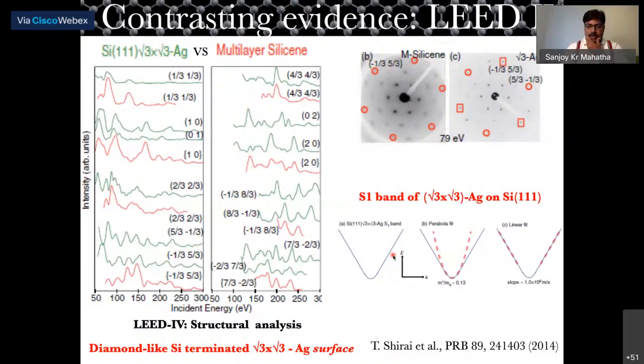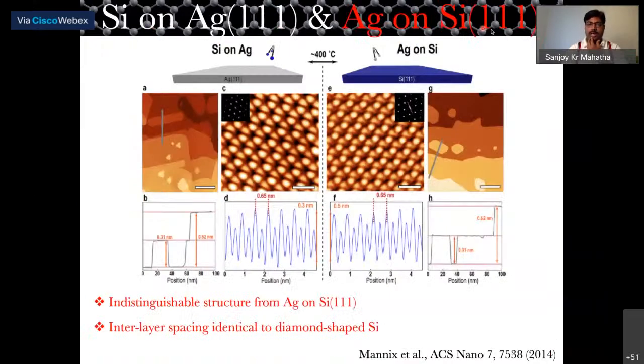A similar kind of experiment was done by another American group and was published in ACS Nano. They did the same thing, silicon on silver and silver on silicon. They did STM, and the structures looked exactly the same, just a little bit focused or defocused. The interlayer spacings and the lattice parameters are also very similar. From here, they say they have indistinguishable structures from silver on silicon and the reverse structure, and the interlayer spacings are identical. Of course, they didn't give any conclusive evidence of what multilayer silicene is.